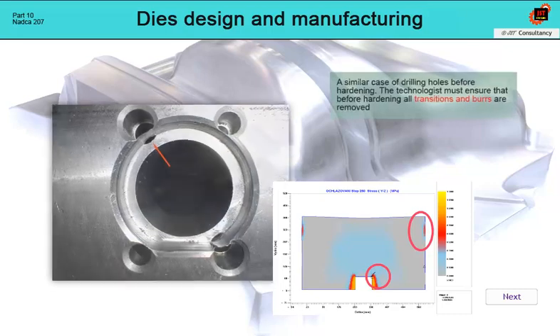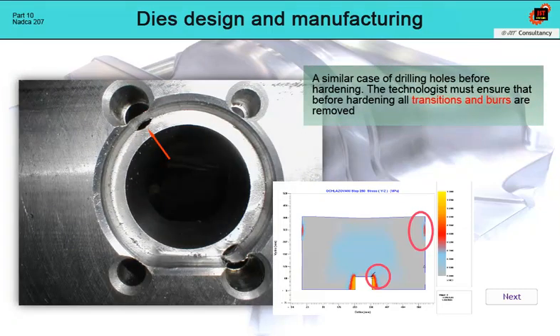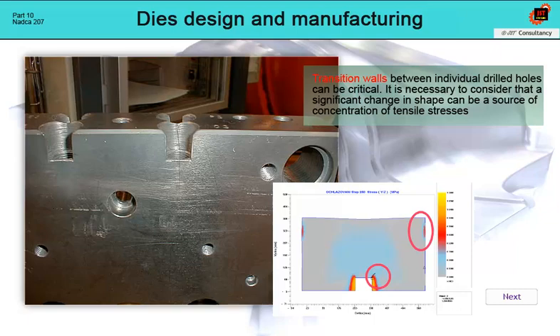Another case of drilling holes. Again, thin burrs after machining can be the source of cracks. Before hardening, it is necessary to remove the listed defects manually or by additional fine machining. Here is an example of drilling cooling channels. Since the transition wall cannot be ruled out from the point of view of the dimensions of the plate and the dimensions of the cooling channels, it is necessary to think about the fact that it must be treated before hardening. Otherwise, due to the concentration of tensile stresses on the outer side of the plate, the parts may crack here.